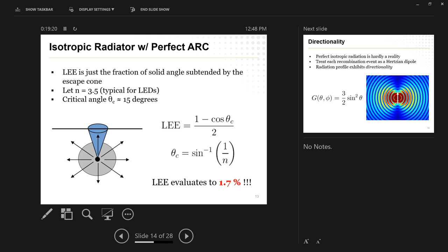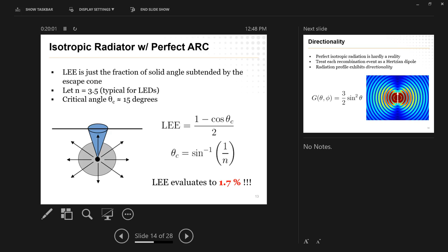So the critical angle just comes out of Snell's Law, and you stick it in there just for kind of an envelope calculation, and what you find is, say, for an index of refraction of 3.5, which is pretty common for semiconductors, crunch out the math, and you get a total light extraction efficiency of less than 2%. So, yeah, in principle, semiconductors, or excuse me, LEDs are fantastic for creating all the light in just the little spectrum that we want, but this problem of getting the light out of the thing pretty much kills it from the get-go. You're less than 2%. So our task is to figure out, how do I get light from in here to just get out there somehow and bring this number back up?